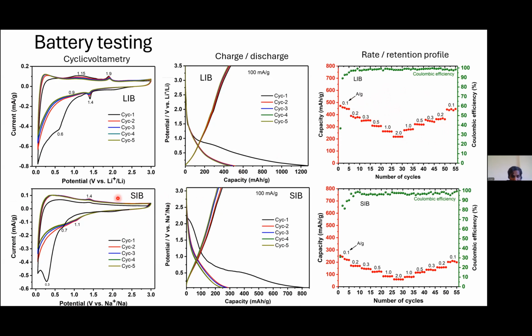And what about sodium ion battery? Remember that sodium ion battery cannot be made with graphite because the interplanar spacing is not sufficient for the intercalation of sodium. But here what you see is a recurring process. Really it is making a reversible, recyclable, rechargeable battery with the sodium. And we have been looking for the replacement of lithium in the battery applications.